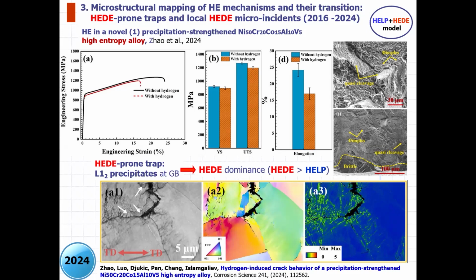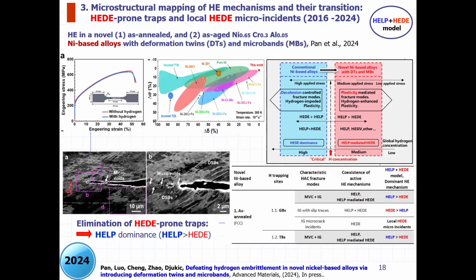And as you can see, we have decohesion and activation of HEDE mechanism on the grain boundary, which is strengthened by these precipitates. So this particular precipitation strengthening high entropy alloy is very prone to hydrogen embrittlement due to the existence of HEDE-prone precipitates and their location in the microstructure. You must carefully provide the metallurgical engineering of high hydrogen embrittlement resistance alloy. And we show how to do that in nickel-based alloy.